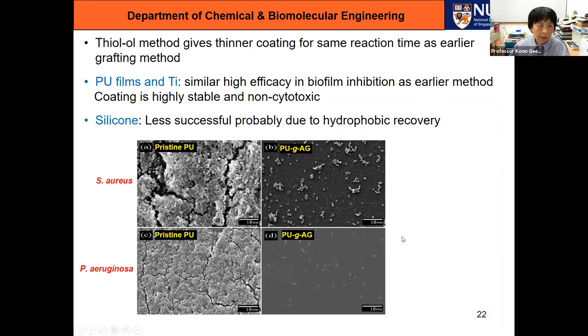We find that this thiol method gives a thinner coating using the same period of time as our earlier grafting method in the absence of oxygen. For polyurethane films and titanium, this is not an issue. We get similar high efficacy in biofilm reduction, as you can see over here. And the coating is also highly stable.